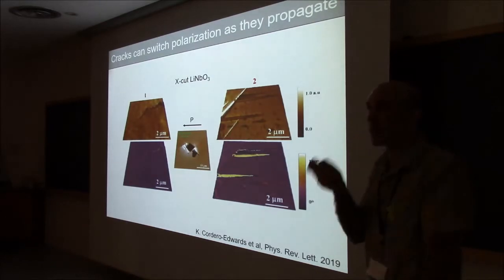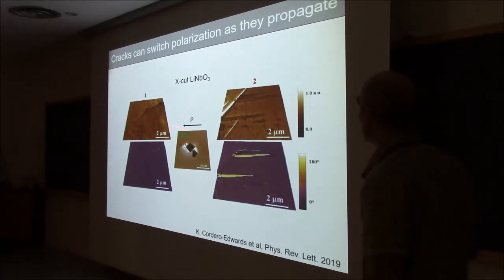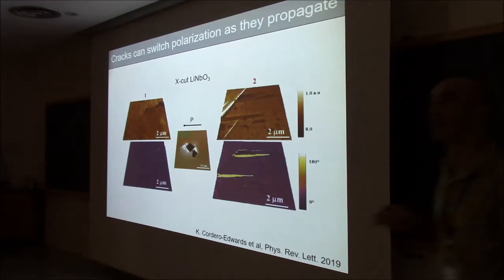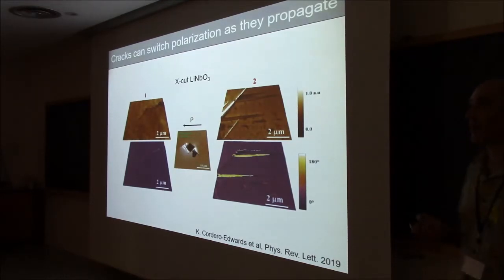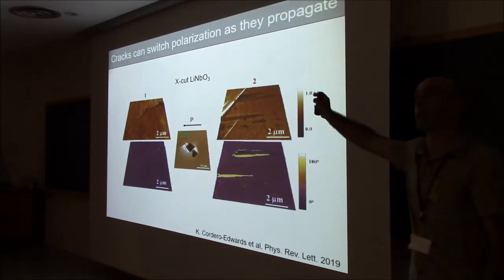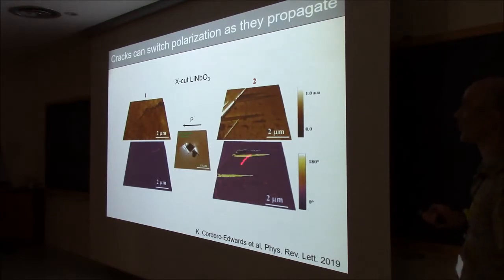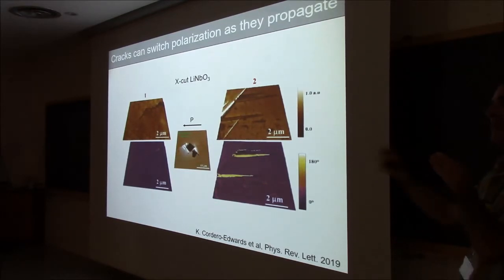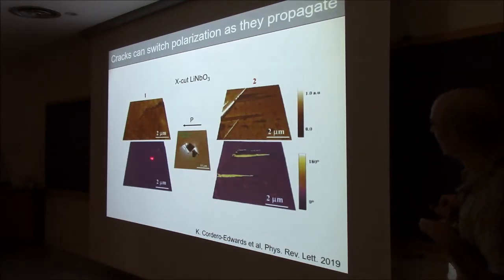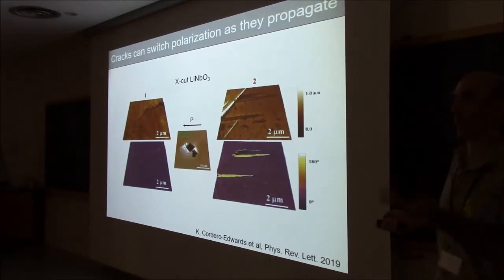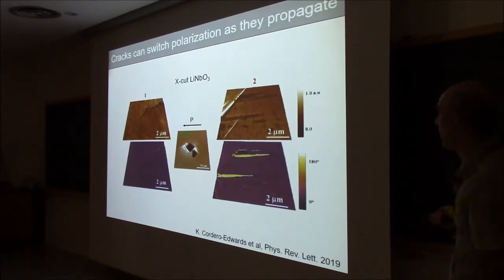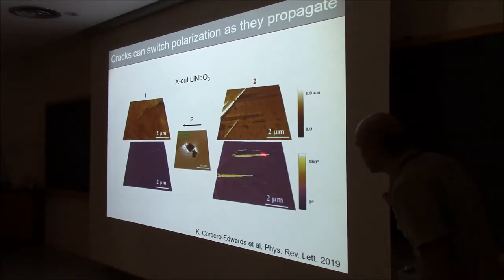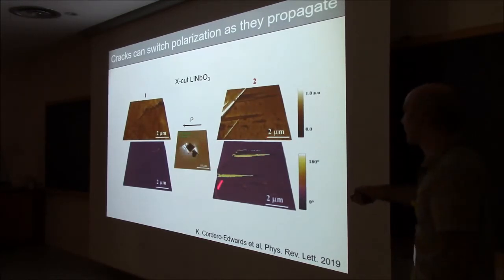They are so big, those flexoelectric fields, that if this crack propagates in a polar material, in a ferroelectric, in this case lithium niobate, it can cause switching as it travels. Right? Of course, it will only cause switching if the flexoelectric field is anti-parallel to the polarization. The crack that propagates in the opposite direction will not cause any switching. So in this case, it did work. We did see a trail of switched flexoelectric domains in the wake of our crack.